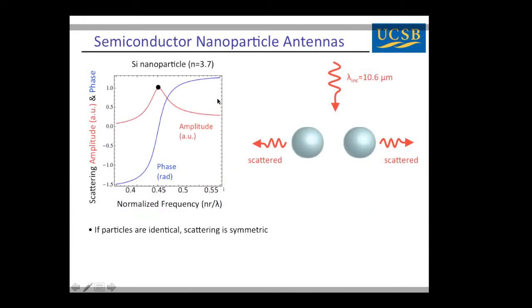Okay? So let's start with two identical spherical particles. What we know is that if we shine light on it, and in my group we're very interested in infrared radiation, so we're going to be looking at light with a wavelength around 10.6 microns. If I shine light, by symmetry, these spheres must scatter as much to the left as to the right. Okay? So we would have a symmetric scattering lobe.